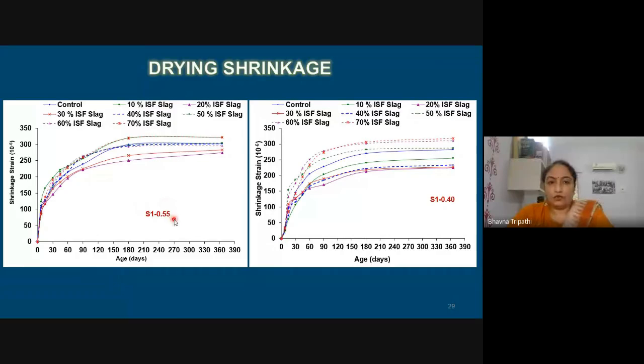Drying shrinkage was tested for a 1 year period under controlled temperature and humidity. It is very important to maintain humidity and temperature control. Otherwise, in summers, you will experience a drastic shrinkage, and when there is a monsoon, you will again see that your specimens have expanded. So, I will discuss the shrinkage results in a tabular form.